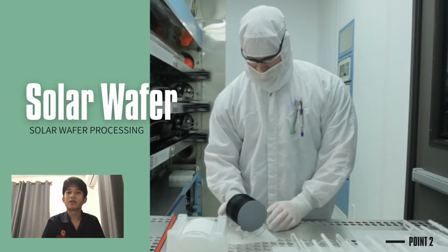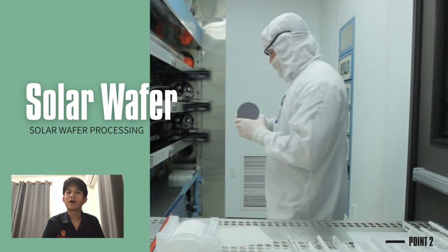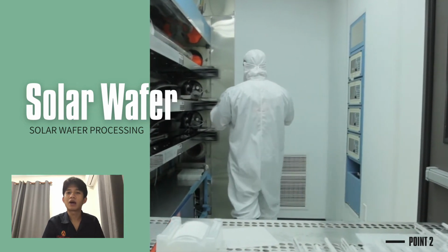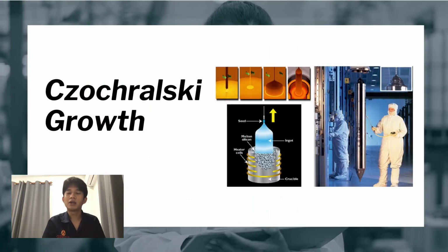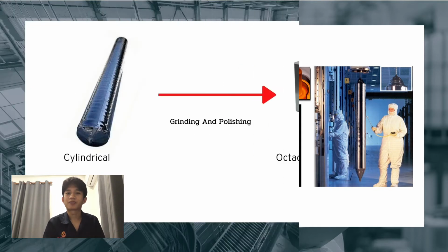To produce solar cells, we begin by making solar wafers. So, in this topic, I will talk about how to make solar wafers. First, we begin by producing a cylindrical silicon rod. It starts from melting the polysilicon at high temperature, then dipping in the seed crystal and pulling it at a controlled speed. It will cause crystal growth. This process is called the Czochralski method.